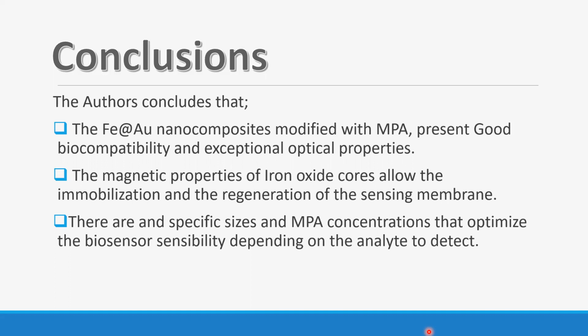Then they also conclude that the magnetic properties of the iron oxide cores allow the immobilization and the regeneration of the sensing membrane, which is important to have a constant signal from the biosensor. And they also conclude that there is a specific size of nanoparticles and MPA concentration, or ligand compound, that optimizes the detection of certain analytes. So if we want to measure another analyte, you need to tailor the size and the ligand compound to optimize the biosensor sensibility.